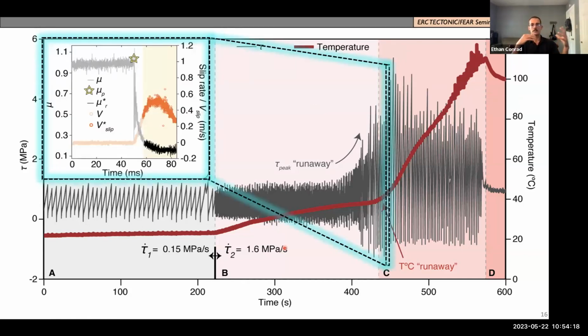But first, let's get calibrated on some of these different variables we're talking about. So zooming into a stick slip event from phase C, these are the terms that I'm going to be using. In the light gray, we have the time versus friction evolution, and it's growing here. In this scale, it's harder to see, but it reaches a peak static strength or peak frictional strength, and then it drops suddenly across some critical slip distance, and then starts sliding at this residual friction or sliding friction or dynamic friction. Those may all be used interchangeably. But the slip velocity, what we're defining as the slip velocity, is this velocity that's happening at the same time as that sliding. So it's the velocity during slip simply.